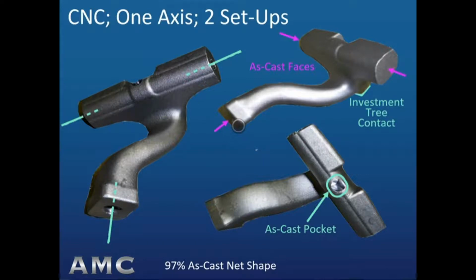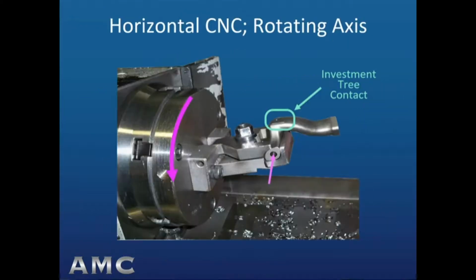At the lower right is an as-cast pocket whose size and position tolerances are met by the capability of the investment process. The design of the fixture for the horizontal CNC machining center is shown here. Holes are drilled and tapped on each side of the casting's T-bar in a rotating fixture. Note that the contact of the investment casting's liquid metal delivery tree is avoided in the fixture design.